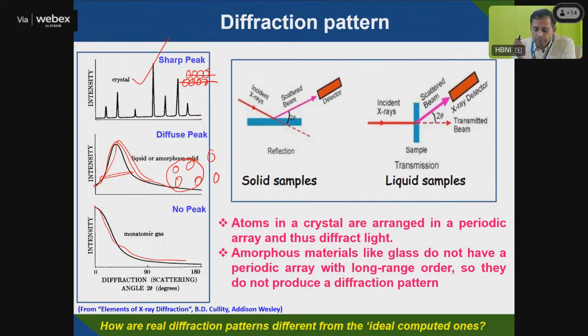But X-ray diffraction can be done in two ways. Commonly, for solid samples the reflection method is used, where the X-ray comes here and scatters back. But for a liquid sample, it is possible to do X-ray in transmission mode. You keep the liquid here, the X-ray transmits through the liquid and goes to the detector. That is mostly used for liquid samples, while for solid samples we go for reflection mode. Amorphous metals and glass don't have a periodic array with long range periodicity, so you will not get a diffraction pattern.